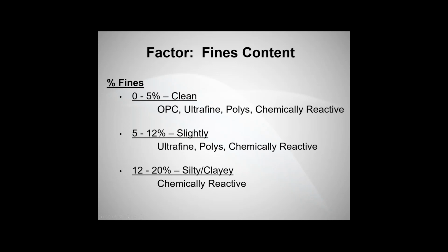So anything from 0 to 5% is considered a clean material. As long as the grain size will allow, you're going to be able to just pump an ordinary Portland cement. You could do an ultrafine, a polyurethane, or a chemically reactive, but because of the cost, you're probably going to go to an ordinary Portland cement as your first choice. Now, as the material gets dirtier to slightly silty, slightly clay, between 5 and 12%, an ordinary Portland cement is going to fall off, and you're going to bounce into and require an ultrafine cement.